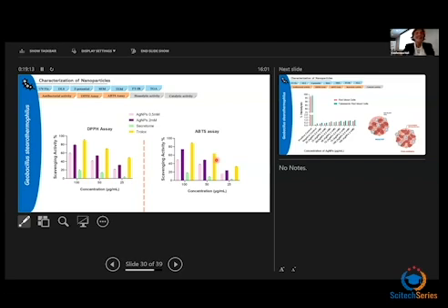We also wanted to assess the antioxidant activity of the produced nanoparticles, and for this we set up DPPH and ABTS assays using Trolox as a positive control. As can be shown, we used different concentrations of nanoparticles, and could observe a dose-dependent effect, in both the 0.5 millimolar and 2 millimolar preparations. The best results were obtained when using the 2 millimolar nanoparticles, and the highest concentration of nanoparticles, reaching values around 80% and 75% scavenging activity.